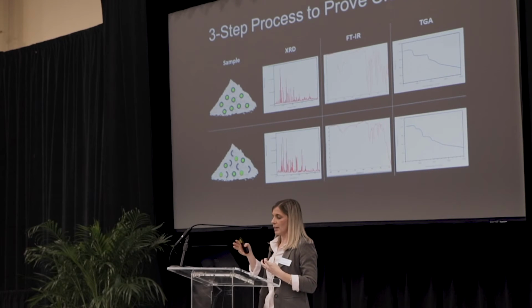We can look at the XRD, and those patterns are different for those two samples. We can look at the FTIR. Those patterns are different for those two samples. And then finally the TGA, and again we can see the difference.